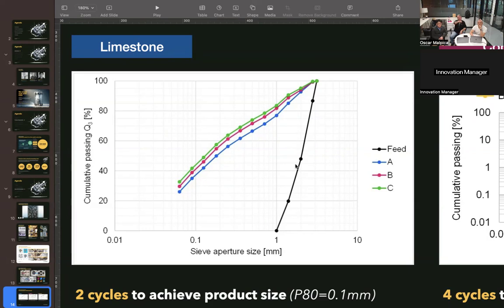So you've got sieve size on the bottom going, in millimeter scale, from 0.01 millimeter, so 10 micron, all the way up to 10 millimeters. And then on the vertical axis, you've got cumulative passing. And that's just a common way of saying the mass of material that passes the sieve at that size. So in this case, the feed was obviously 1 millimeter to 3 millimeters in size at 100%. And then the products from each of these 3 test cycles show that if you were targeting, for example, say a 100 micron or 0.1 millimeter size fraction on this chart, we're getting 40% of the mass of material passing that size pretty much for each test cycle.